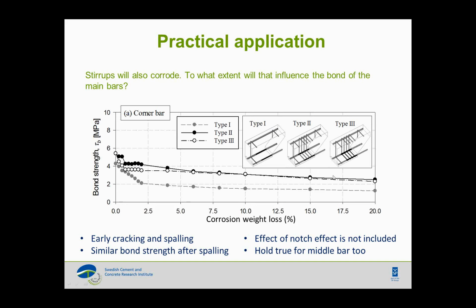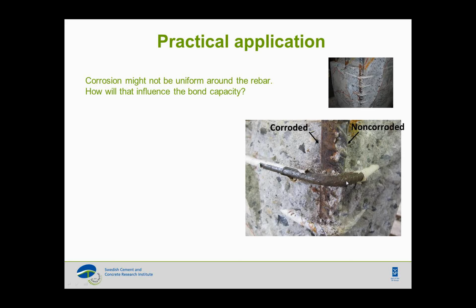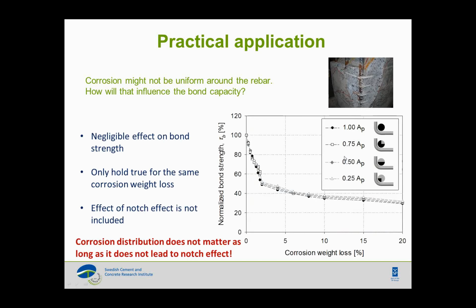And then the third question is that we might not always have uniform corrosion. Usually we get corrosion on one side, half of a bar or a quarter of a bar. Like in this case in our specimens, if you have sharp eyes, you see that on the left side we have had corrosion, but nothing on the right side. So we tried to run our model for different corrosion distributions around the main bar, and what we see is that it doesn't actually influence the bond strength at all in this case, in this geometry that we were looking into,